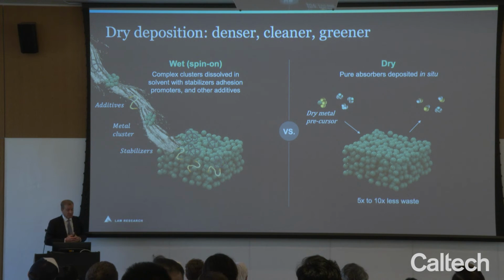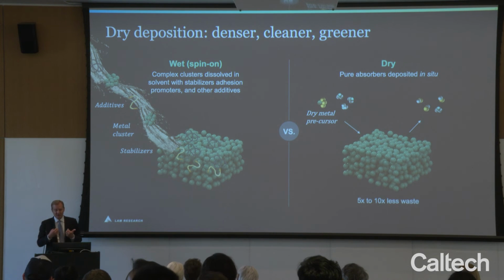There's one other benefit as you change from wet to dry processing, again, coming back to environmental impact. The truth is that as you spin materials on a wafer wet, more than 99% of that material actually just is spun off the wafer and wasted. And so we found that by converting this into a dry deposition process, where we're much more in control of the reactants inside the process chamber, we can reduce the chemical waste by 5 to 10x. So again, something that becomes very important as you think about processing millions and millions of wafers per month around the world.